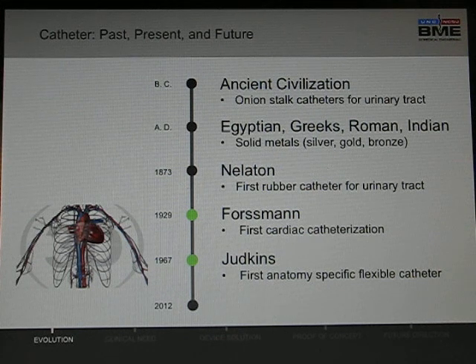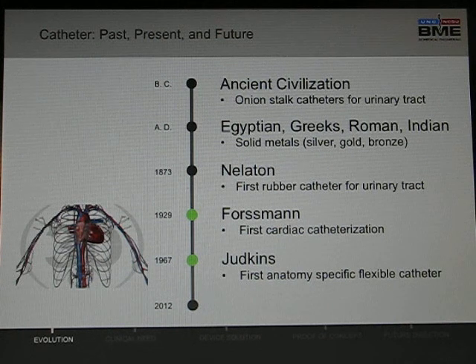Like the early Egyptians, Greeks, and Romans, Dr. Judkins realized the importance of shaping the catheter. He took individual patient x-rays, then using a stainless steel wire shaped it to match the aortic anatomy, placed this shaped stainless steel wire inside a polyurethane catheter, placed the polyurethane catheter in a hot water bath. The polyurethane catheter took on the shape of the stainless steel wire. He inserted the polyurethane catheter through the femoral artery of the patient and was able to use the catheter to access coronary arteries.